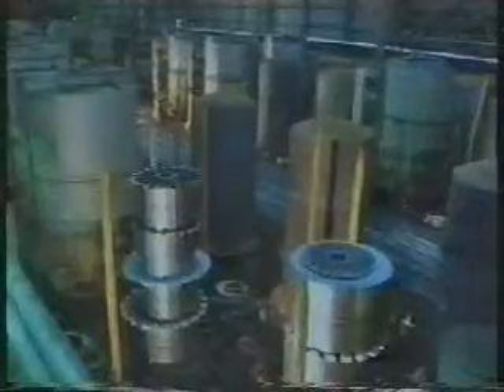One disadvantage is that the strip steel does become work-hardened by this method of cold rolling. Some cold-rolled steels tend to crack if they're used straight away. This can be prevented by annealing. The coils are heated in an inert gas atmosphere. The absence of oxygen prevents scale appearing. The coils are kept at 700 degrees centigrade for 72 hours, and then allowed to cool slowly in their protective blanket of inert gas.